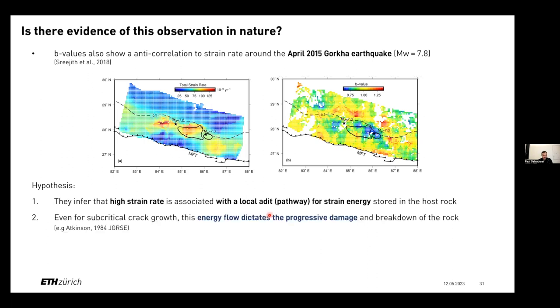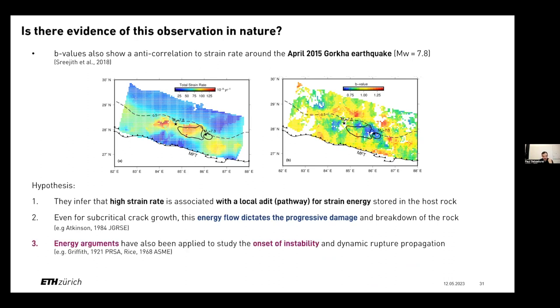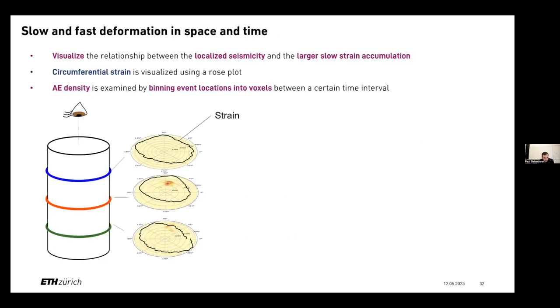So strain rate actually is consistent with subcritical crack growth, where energy flow dictates where progressive damage occurs within the rock mass, such as in the very seminal studies by Atkinson. And even energy arguments and the flow of energy have also been linked to determining the onset of instability, from Griffith to Rice, and control dynamic rupture propagation. So these might be some interesting findings to investigate, and we're looking into them right now to get a more concrete understanding of strain rate and B-value dependence. That's one of the main findings that we're trying to emphasize here.